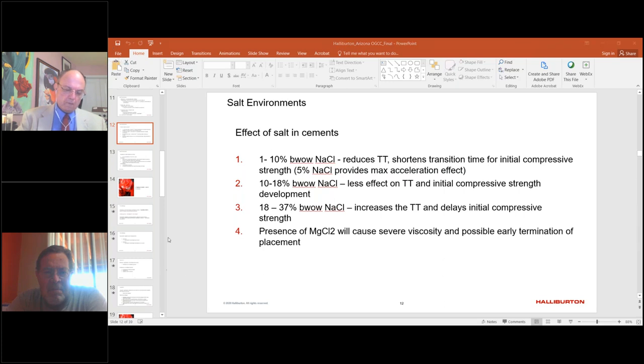Once again, the fourth bullet point there, if you've got tachyhydrites, magnesium chlorides, they are very unpredictable in the presence of cement and can lead to hydration and possibly flash setting of the cement. So magnesium chlorides need to be dealt with slightly differently. And we have a product called Salt Shield to be able to cement through a tachyhydrite, a magnesium chloride situation. So really, to analyze the salt that you are going to be cementing through, get a sample and run it through the laboratory, XRD, X-ray diffraction, and understand its chemical makeup so that we can choose the right solution would be highly recommended. Next slide, please.